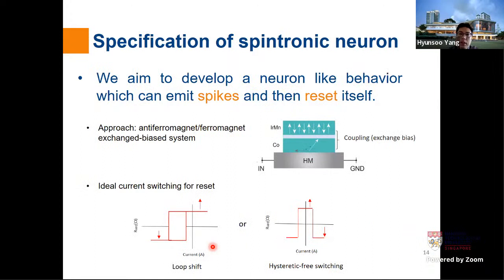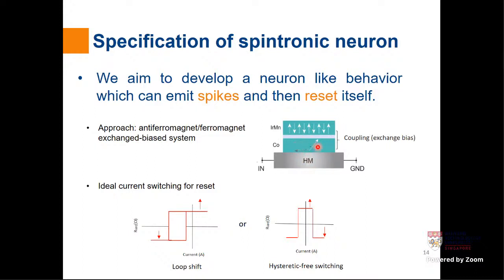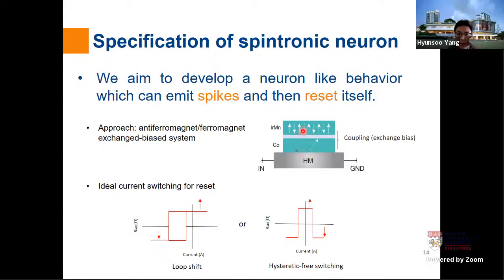So our approach is to utilize exchange bias using a ferromagnet and an anti-ferromagnetic material. So if you have exchange bias, you can shift the MH curve in one direction. Then if you measure the spin orbit torque signal in those devices having a heavy metal underneath, and you apply current here, you can switch this Co layer into a certain direction. Then what will happen? Because of exchange bias, this magnetic moment or spin direction can come back to the initial direction. So once you go back to the zero excitation current, it will move back to the initial state. So that is our main motivation.